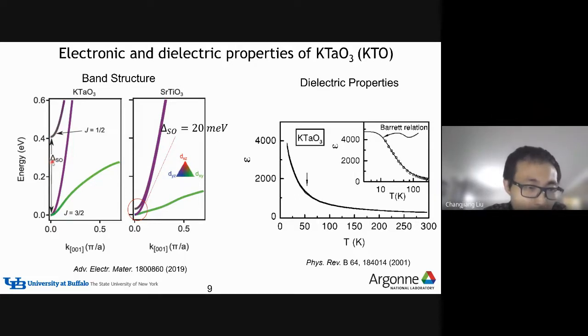You can see here, this delta SO, basically spin-orbit coupling, splits the J equals 1/2 and J equals 3/2 orbitals by as high as 0.4 eV, while for this one, the spin-orbit splitting is only 20 milli eV. So this is quite distinct for KTO. And KTO is also showing very interesting behavior at low temperature, similar to STO. At low temperature, KTO also showed a very large dielectric constant. This is because both KTO and STO are incipient quantum ferroelectric materials. Basically, they are very close to forming a ferroelectric at low temperature, but just because of the quantum fluctuation, they eventually do not become ferroelectric.